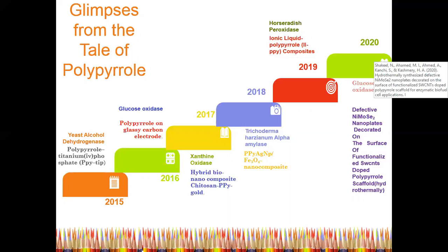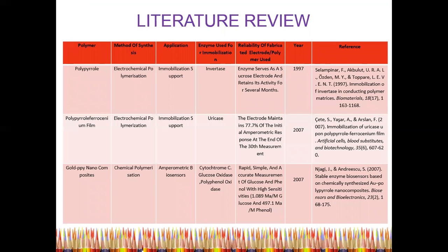Now, in 2018, Trichoderma harzianum alpha amylase was immobilized onto polypyrrole iron oxide nanocomposites. Horseradish peroxidase was immobilized onto ionic liquid polypyrrole composites in the year 2019. In 2020, glucose oxidase was immobilized onto a novel defective nickel molybdenum selenide nanoplates decorated on the surface of functionalized single-walled carbon nanotubes doped polypyrrole scaffold. These are certain literature reviews we have carried out. In early 1997, invertase was immobilized onto polypyrrole prepared by electrochemical polymerization. And in 2007, a polypyrrole ferrocenium film was used as the immobilization support to immobilize uricase enzyme.